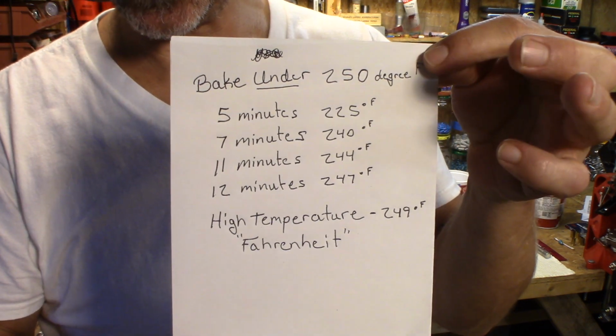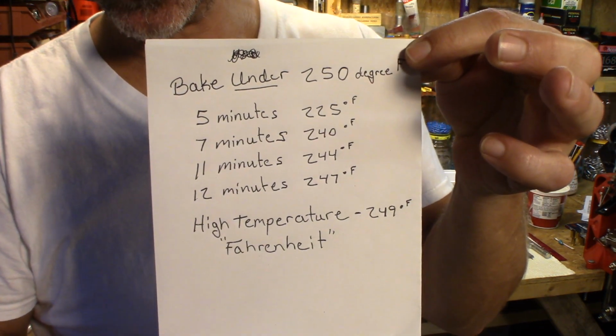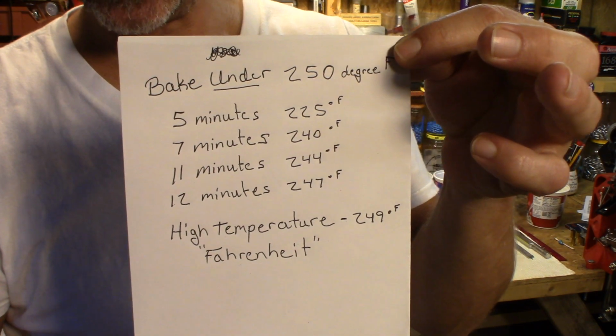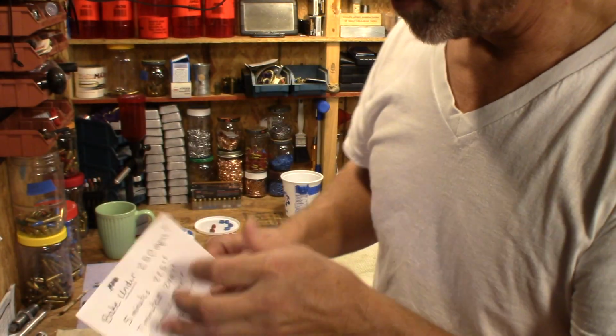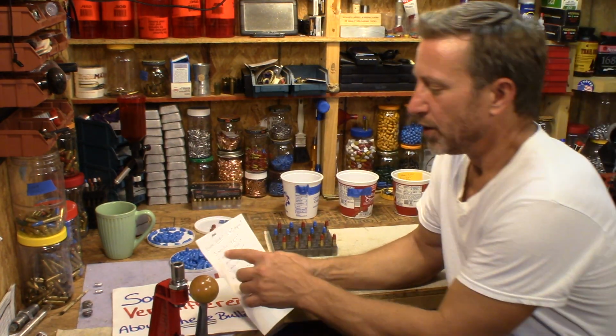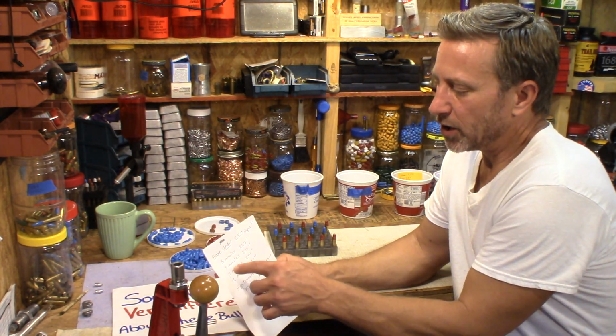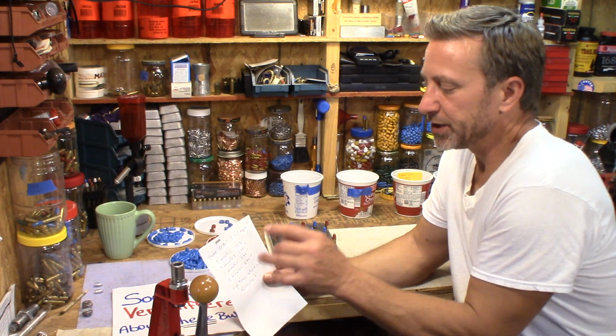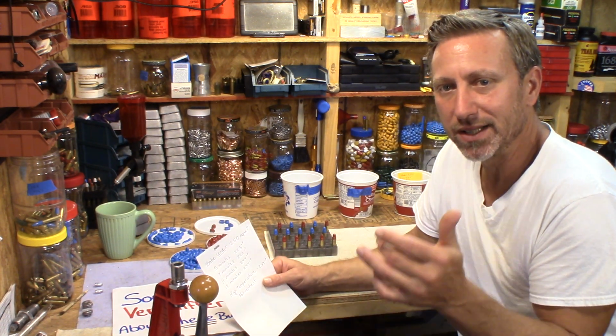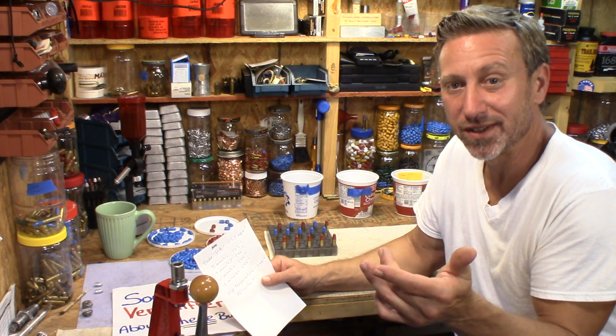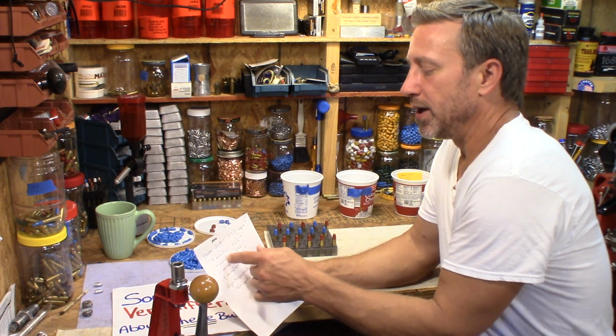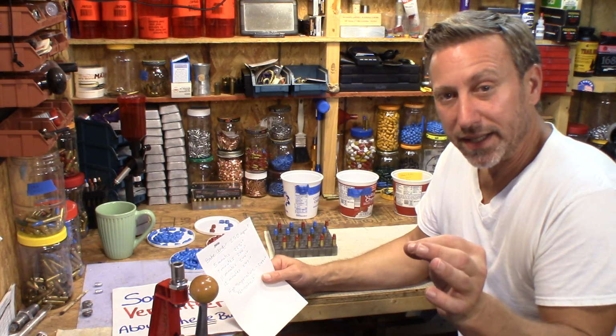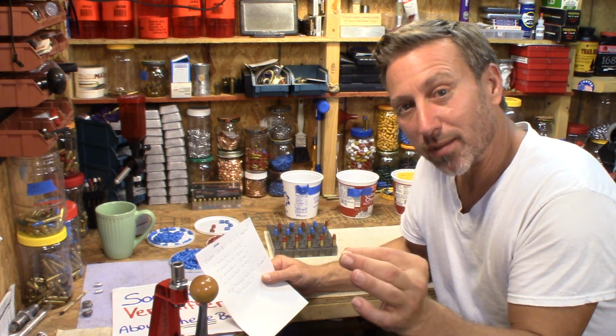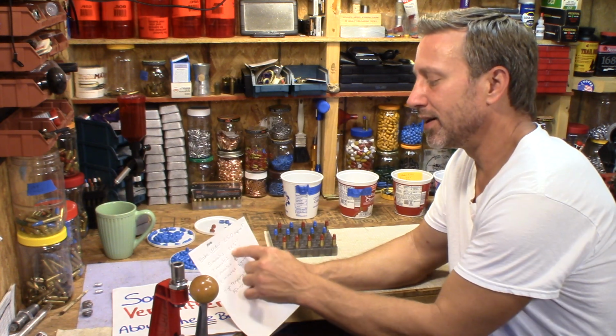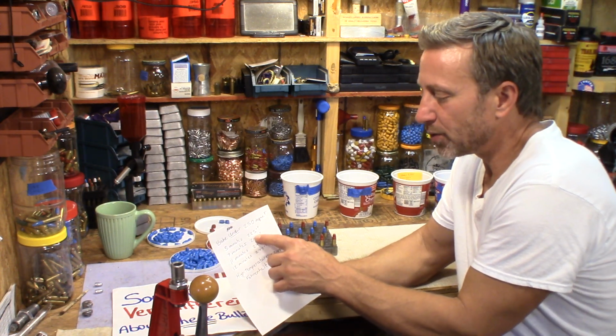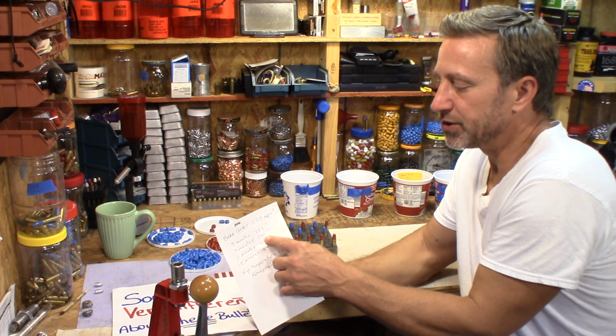I'm going to show you this. You can freeze, pause, just so you can see, and then I'm going to tell you what this means. So you bake it under 250 degrees. I tested this with my PID controller that Johnny's Reloading Bench sent me as a gift. Thank you, Johnny, again. I touched the tip of it to the wire basket while it was in the oven, and at 5 minutes I was at 225 degrees. At 7 minutes I was at 240.